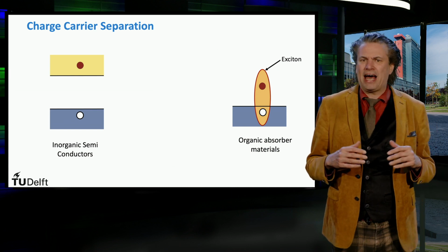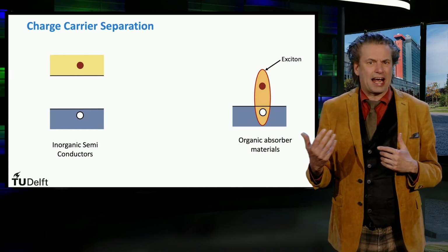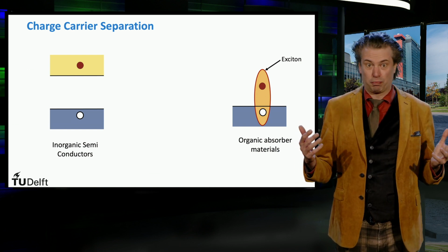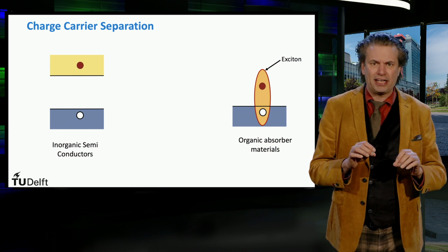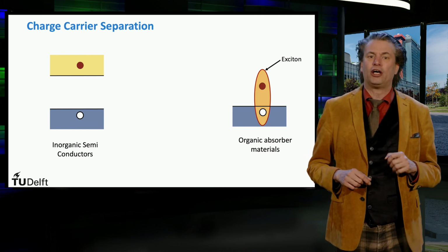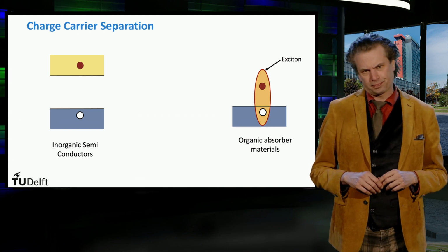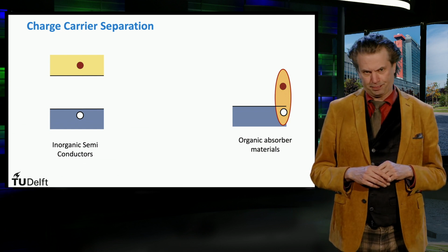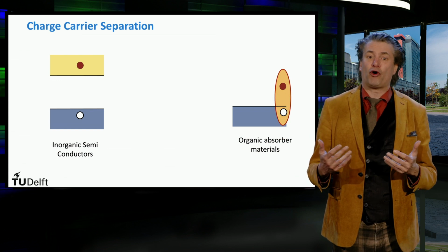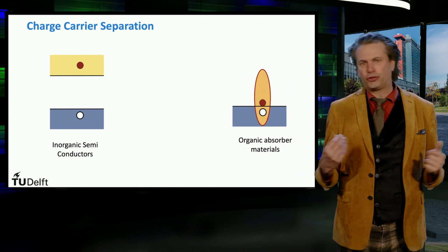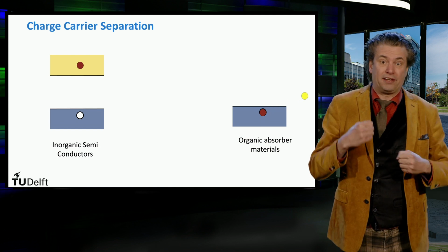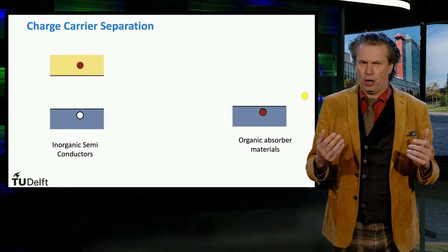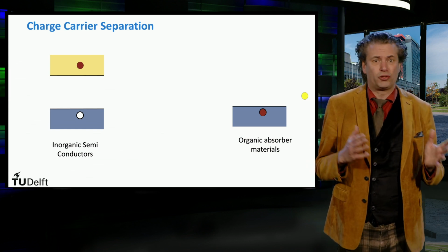The exciton can be imagined as a sphere containing the electron and the hole bound by mutual Coulombic forces of attraction. The splitting of electron and holes does not take place unless the exciton is subjected to a strong electric field. An important limitation posed by this exciton is the small diffusion length. The small diffusion length is a result of high recombination rates. Due to the stronger binding forces between the hole and the electron, the likelihood of electron-hole recombination is very, very high. Under normal conditions, the diffusion length of these excitons is 1 to 20 nanometers.